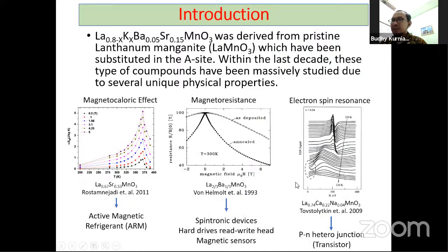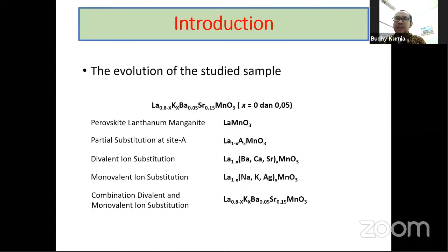But in this presentation, I would like to give my emphasis to the first condition, the magnetocaloric effect. From this curve, we see that the minus delta entropy is the main thing that characterizes the sample for the magnetocaloric effect. In this slide, we see that the value of the minus delta entropy is about 5 in this sample. So we want to explore our sample on this basis. And for the evolution of the studied sample, we have a history of the sample.